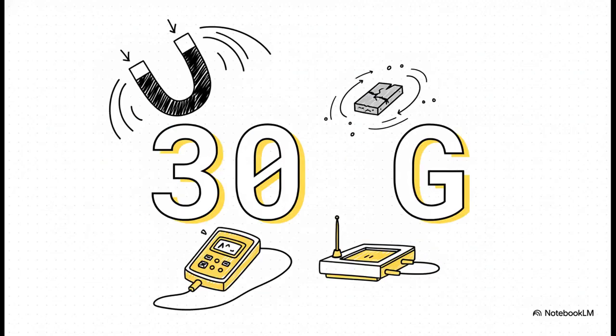Now, how do you know when you've actually established a strong enough magnetic field? When you're measuring the tangential applied magnetic field strength with a Hall effect meter or Gauss meter, the absolute critical threshold you need to memorize is a minimum of 30 Gauss. That equates to 2.4 kiloamps per meter. If your field strength drops below 30 Gauss, you're risking not forming a visible indication at all.